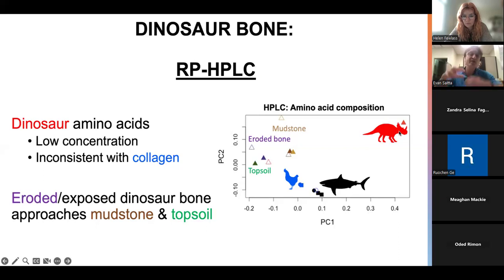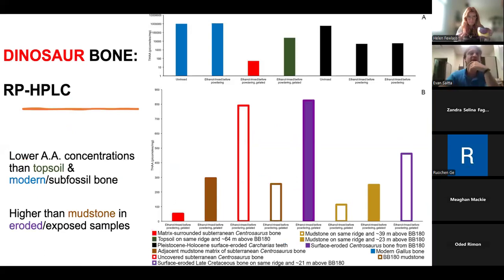But with bone that was either eroded onto the surface or more heavily exposed during excavation, that Centrosaurus bone actually begins to converge upon an amino acid composition more similar to either the mudstone or even the topsoil, which is interesting, suggesting that recent amino acids are infiltrating these bones as they erode out and sit upon the surface.